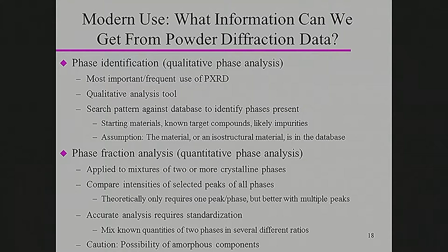Okay? One thing to be careful about is there is the possibility of amorphous components. They contribute weight, but they don't contribute intensity to your diffraction pattern.